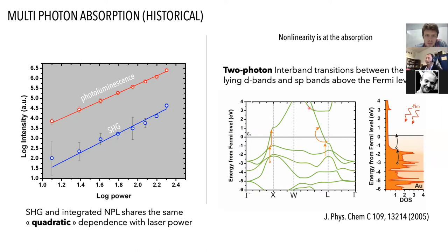And so this two photon absorption can take place between this D band all the way to the sp band via multi-photon interband transitions, where you will first promote an electron from the D band to the sp band through one photon transition, and then you can have the second photon absorbed to promote a hole lying deeper in the D band and fill the gap here basically,